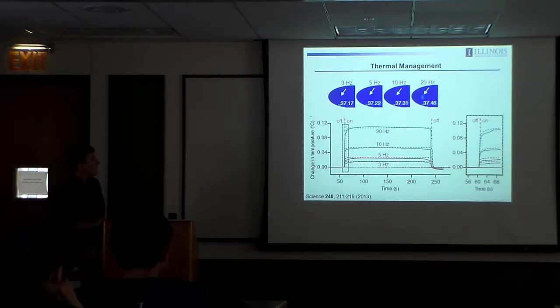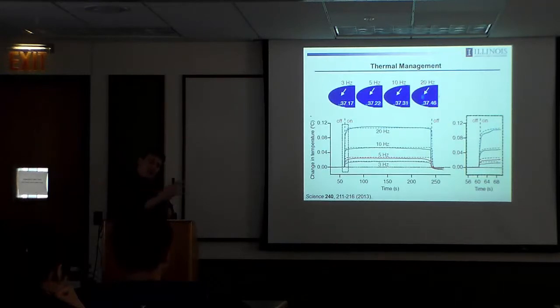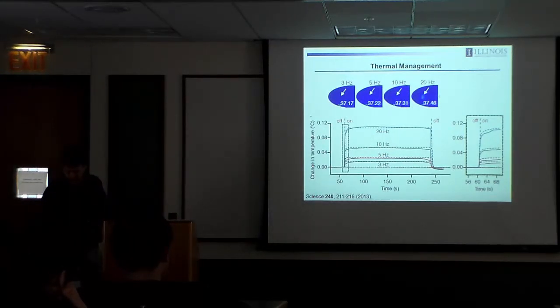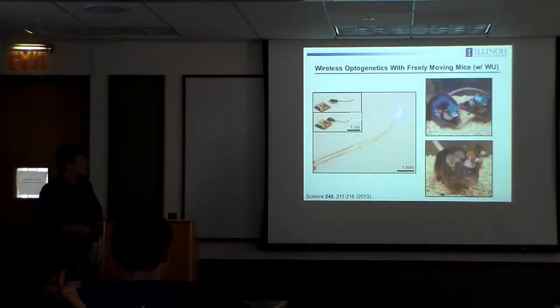That's extremely helpful. And then the other thing is in the living system particularly, and you can see the delta T in the living system is much smaller than that in this explanted brain sample. And that's because the blood flow, the circulation through the vasculature next to the LED is actually heat sinks. So it's pulling heat away from the devices. So even at the highest repetition rate, the peak temperatures are less than or about comparable to about 1/10 of a degree. So that's more than a factor of 10 smaller than it needs to be in order to avoid adverse effect of the heating.